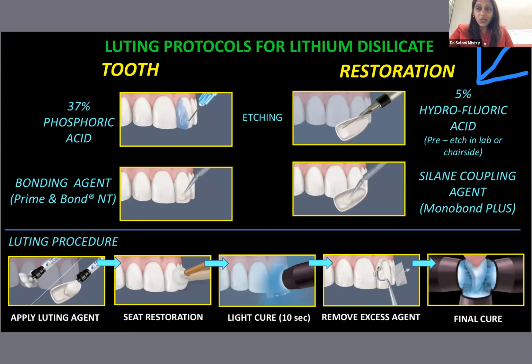After that, you apply a silane coupling agent, Monobond Plus, and a lot of other silane coupling agents are available in the market. You apply the silane coupling agent onto it, air dry it, and then wait for some time. So this is the first thing that you need to do. After the hydrofluoric etching, you wash the veneer or the crown, clean it, and air dry it. Again, apply the silane coupling agent, then air dry it and wait. So this is the preparation of your restoration.